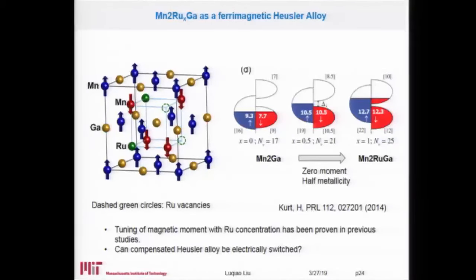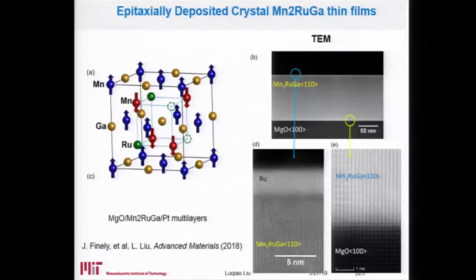So originally, you would think that this is probably contradictory, but it is actually possible to realize in this type of system. Our goal is to utilize this type of ferrimagnet and show that we can also realize magnetic reading and writing. So we tried to repeat those works by first depositing manganese, ruthenium, gallium on top of a single crystal MgO substrate. Here we utilize magnetron sputtering to grow manganese, ruthenium, gallium onto the substrate. As you can see, we can realize almost epitaxial growth using this technique.